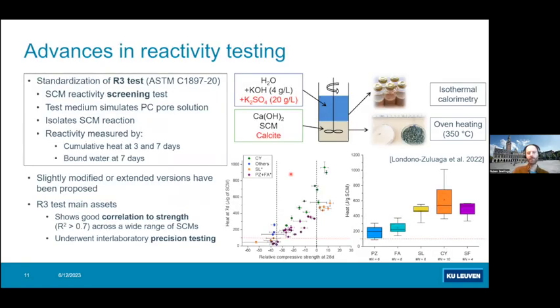About these new test methods, there is a test method being forwarded by a RILEM committee and also adopted by ASTM now, which is called the R3 test. It's an SCM reactivity screening test in which the SCM is tested in a medium which closely resembles the pore solution of a Portland cement. It contains calcium hydroxide, an alkaline potassium solution, and some water. It's mixed together, and you have a fairly fluid paste. In this paste, the only reaction occurring is the reaction between the SCM and the portlandite, so really only measuring intrinsic reactivity of the SCM, with no interactions with the Portland cement. In that way, you can measure the reactivity from the heat release by isothermal calorimetry.